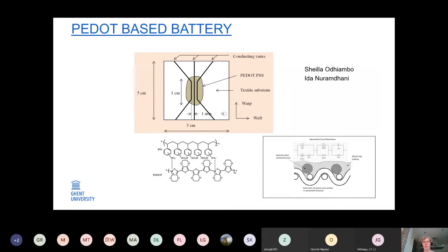Now, here in this slide, we mentioned stainless steel as conductive yarn, but we also looked at silver and copper yarns, and it turned out that this is having an impact. So every element has an impact, but it also gives you an idea of the size of a battery. So it's really small. It's 1/4 up to half a square centimeter.